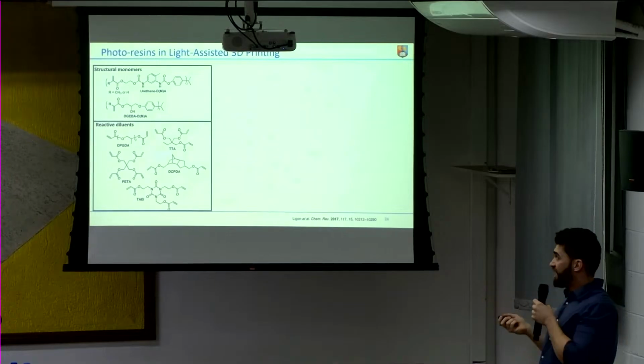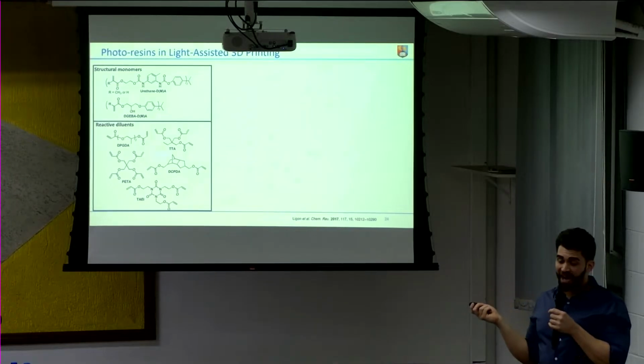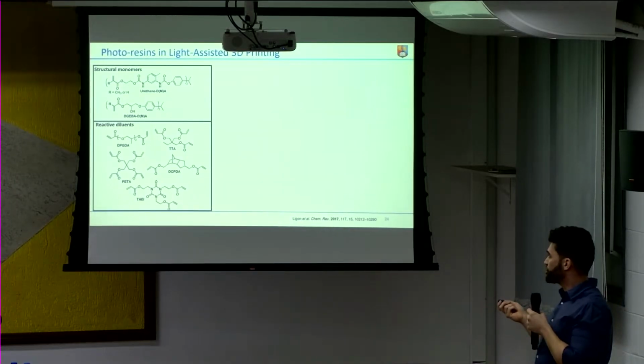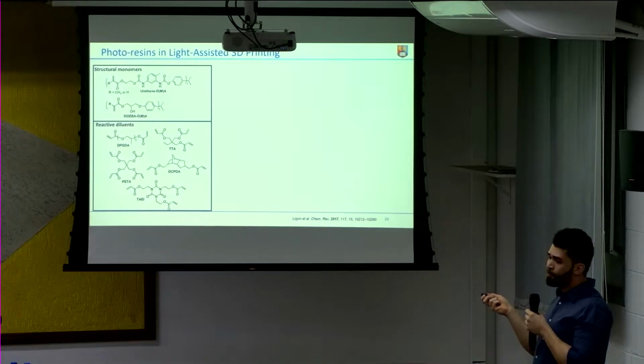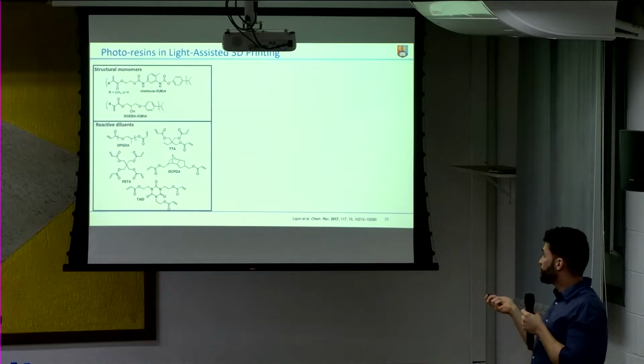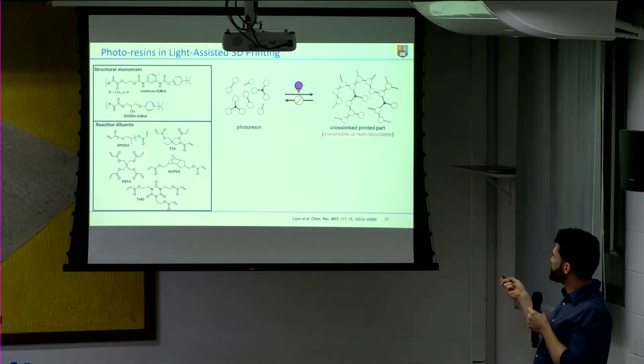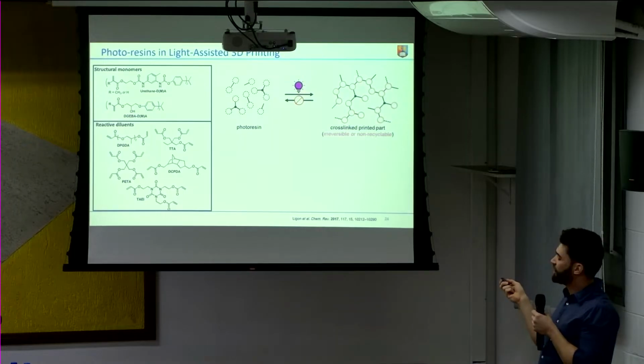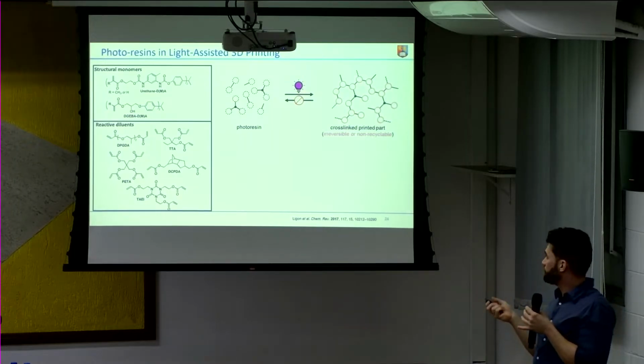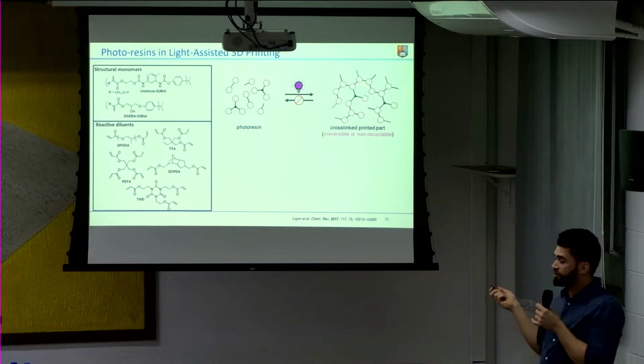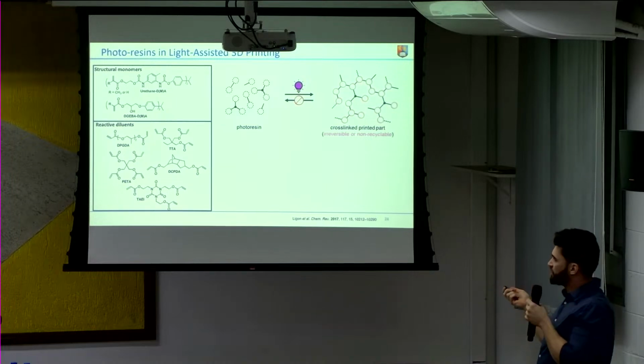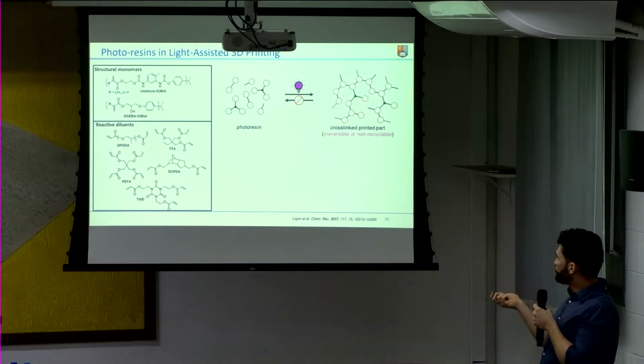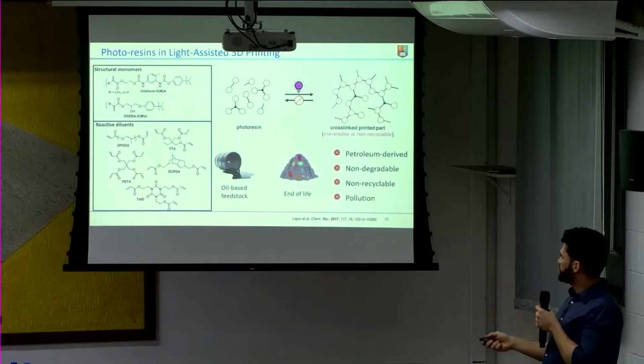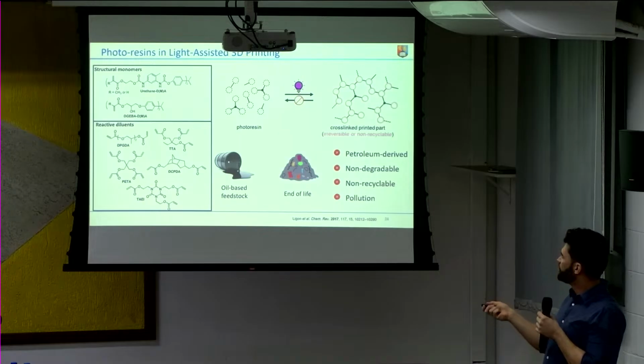But what's the problem with that then? The photoresins that are commercially available are mostly based on acrylate chemistry. Which means that once the photoresin is cured, we have this network here that cannot be recycled. So it just goes to landfills. So not very sustainable. And also the monomers and the diluents are petroleum derived. So we have a problem of source and a problem with end of life.